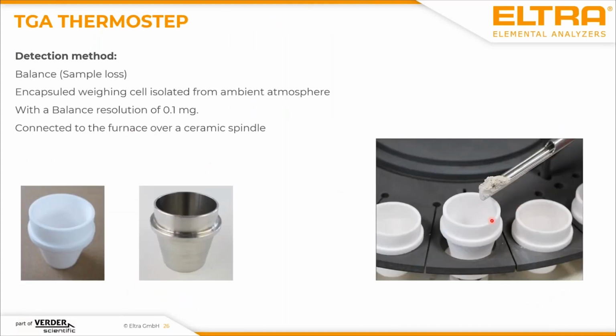You see here, for example, the crucibles where you put your sample in. We have them ceramic. Sometimes it's better to use metal, depending on how aggressive your cement is. If it has a very high SO3 content, you might prefer metal crucibles. And the weighing cell, this is also important, is encapsulated, so it does not come in connection. It does not see the gases coming out of your cement, especially SO3. So this gives you a very long time stability. And the carousel itself is connected over a ceramic spindle. You can have it in ceramics, you can have it in metal. So there is a lot of options for this depending on the type of cement you are looking at.